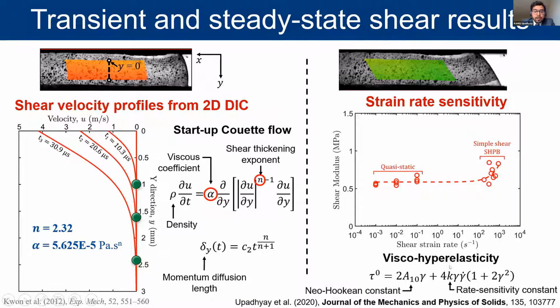And K here is basically directly related to the linear rate of change of modulus with strain rate. So K can only capture a linear rate sensitivity. And this is a simplification that I make here in the modeling. If I were to use even more complicated terms in the actual generalized model, then I could model a higher order variation between the modulus and the strain rate, such as a quadratic or cubic dependence.